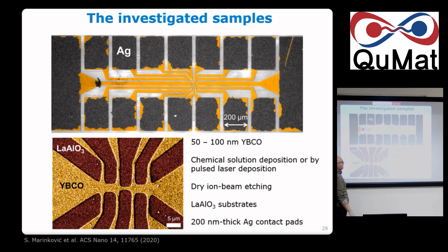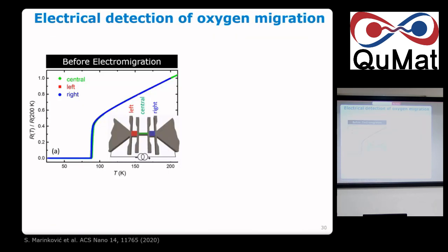Okay, and this is how it looks like, resistance versus temperature. The pristine sample, so I didn't move a single oxygen, everything is monolithic, it's all the same. I put three curves where I measure the resistance of the blue part on the right, the green in the center, and the red, and you see all of them are the same.